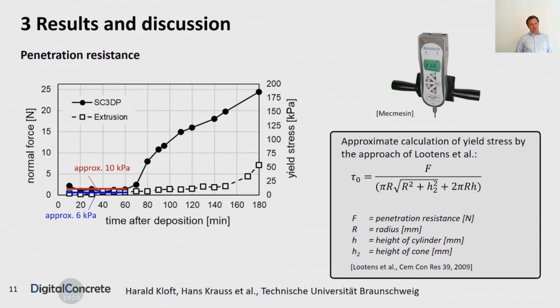And this may be due, on the one hand, to the higher bulk density, as I will show on the next slide, and on the other hand, due to an assemblage of sand grains in the middle of the sprayed layer, which is typical for spraying processes.